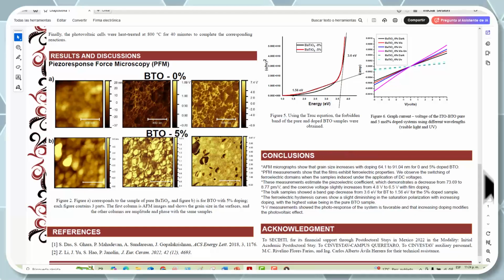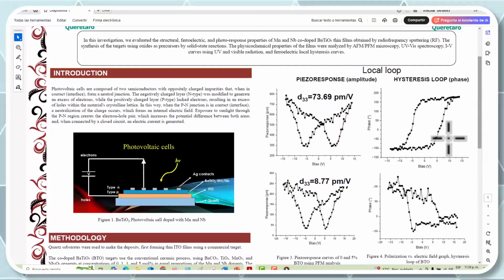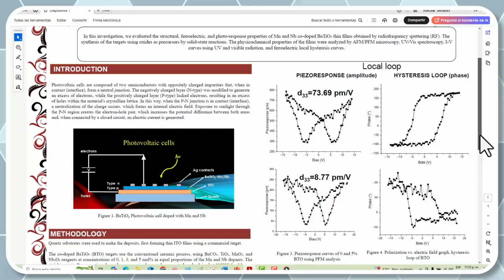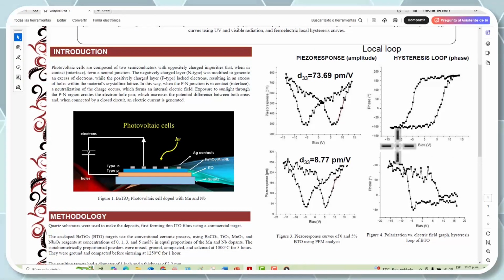Figures 3 and 4 show the local results of the hysteresis and strain curves at specified points on the surface of the BTO samples and the samples with 5 mol percent dopant respectively. Figure 3 illustrates the point strain curves upon application of an external voltage. These curves exhibit the characteristic butterfly shape typical of piezoelectric deformation.